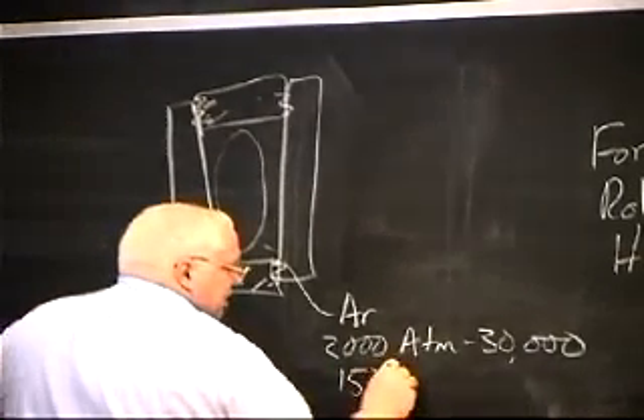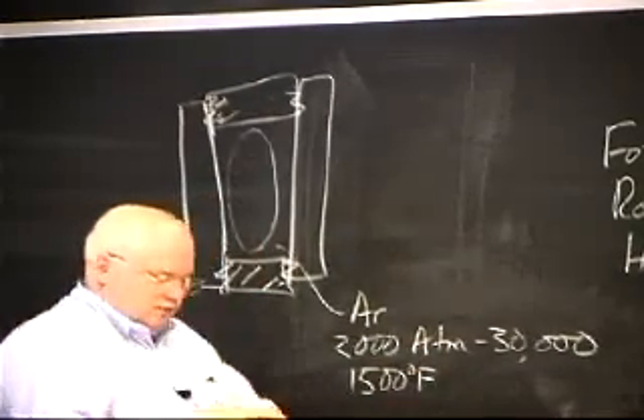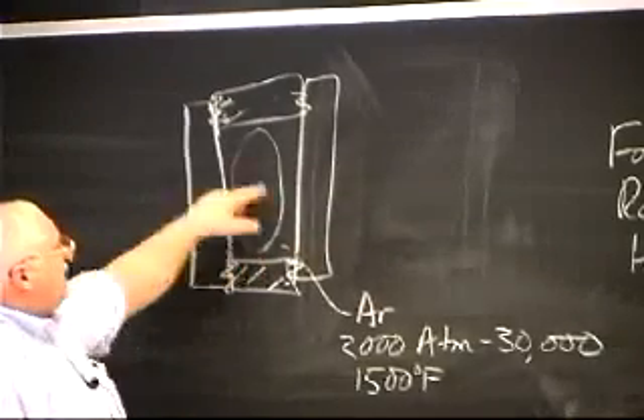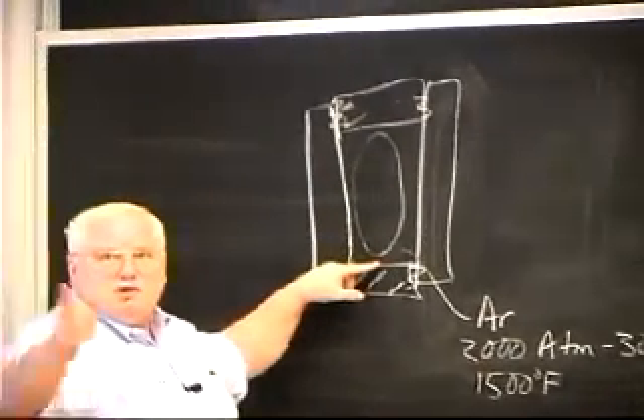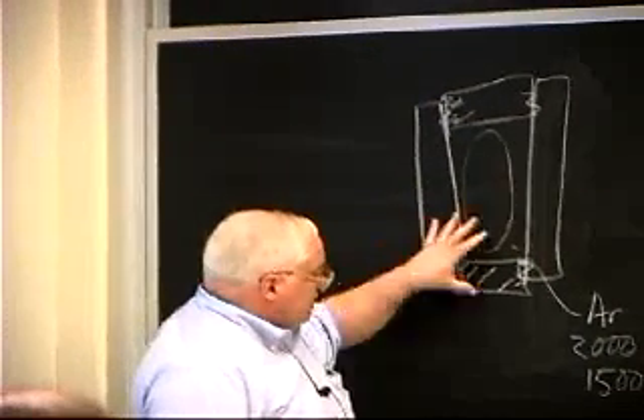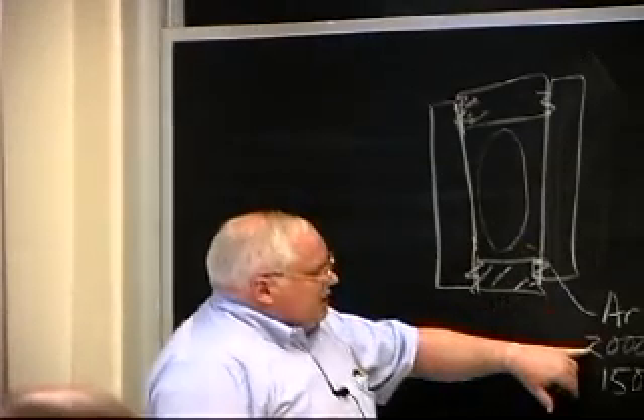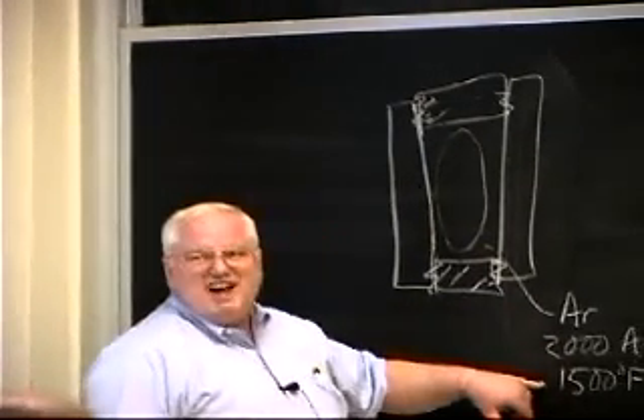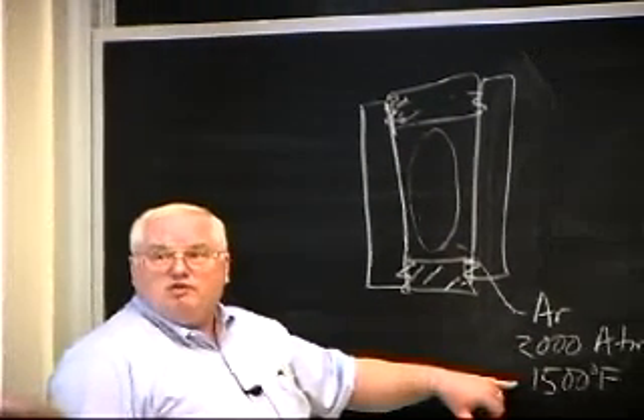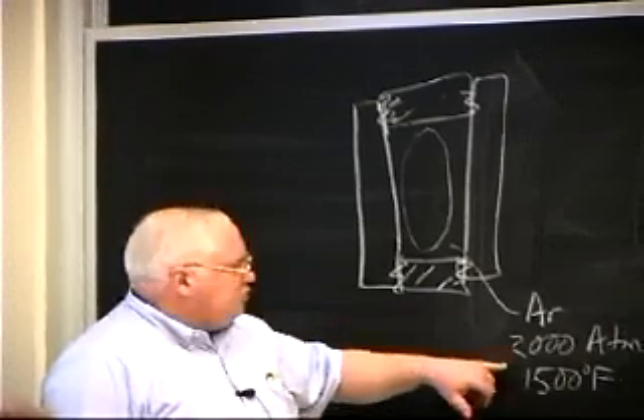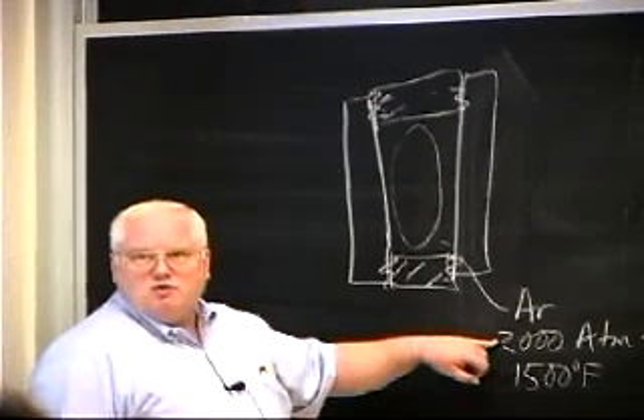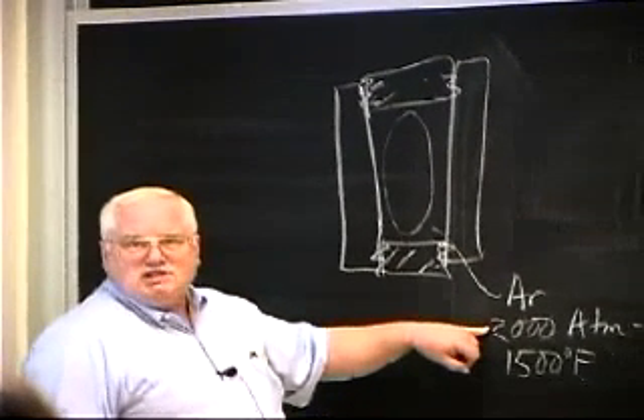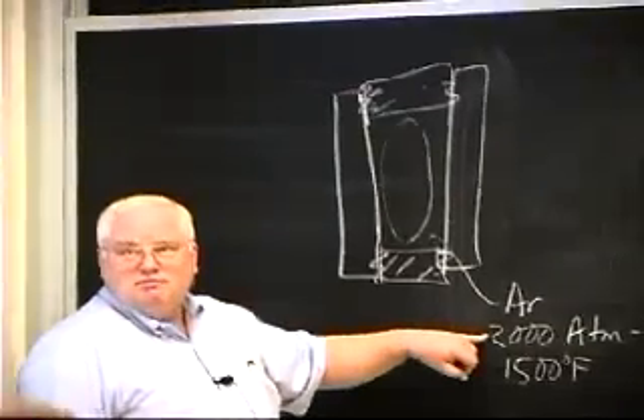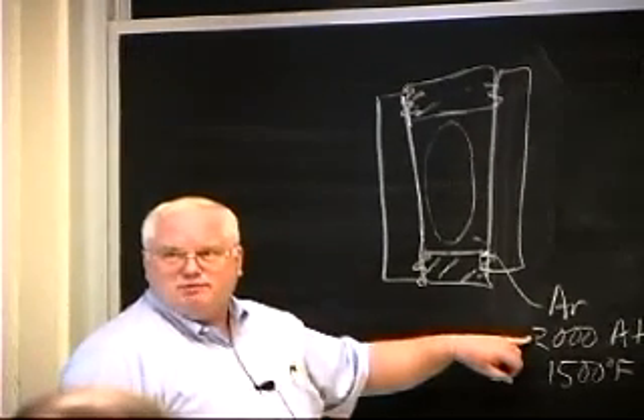1,500 degrees Fahrenheit. I have a little one of these that has a 4-inch diameter by 7-inch chamber in the lab, which costs about $100,000 for that unit. And it goes to 2,000 atmospheres and 2,000 degrees centigrade because it has a graphite furnace. So it can go to very high temperatures. 2,000 atmospheres for a gas, it has about the same density as a liquid. It's gaseous, but it has about the same density.